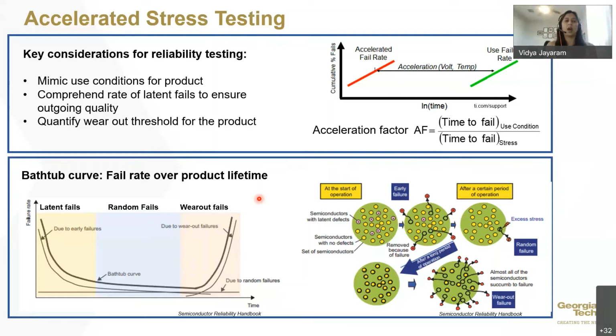So I think what's interesting about performing this kind of stress testing is that no matter what the use condition, no matter what kind of reliability test you're performing, you would see a similar kind of bathtub curve for the failure rate predicted over a product lifetime. In the beginning, you would see latent fails or early failures.